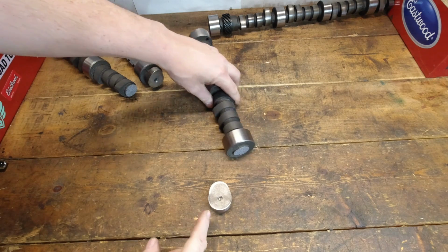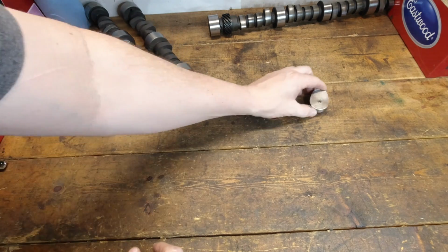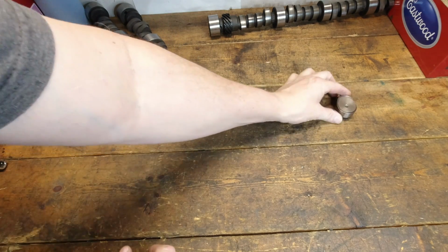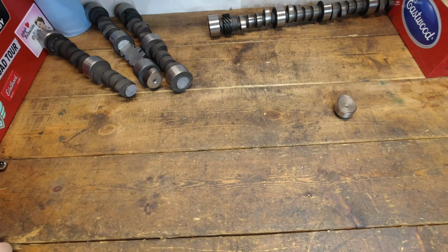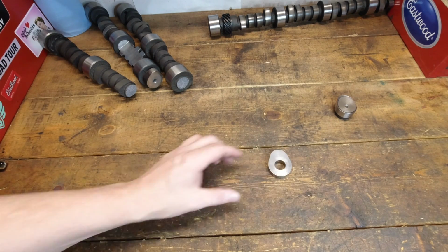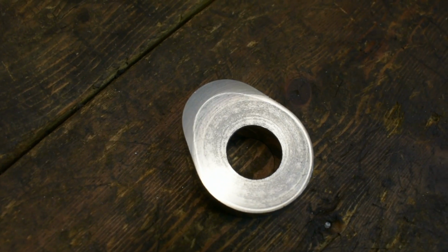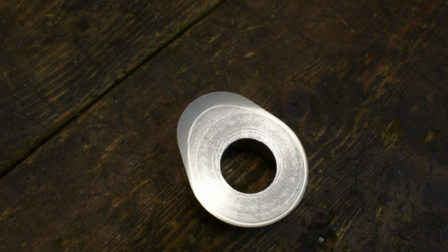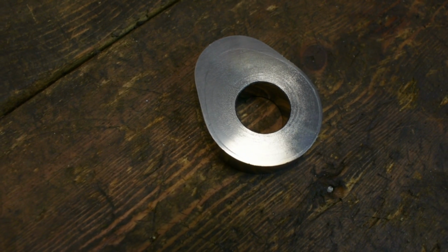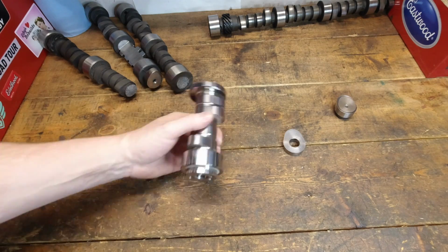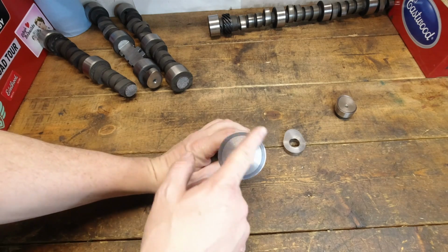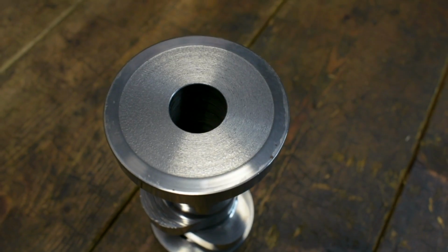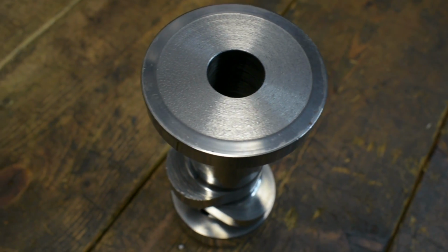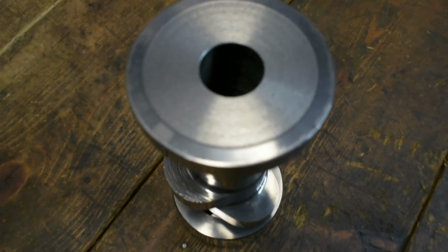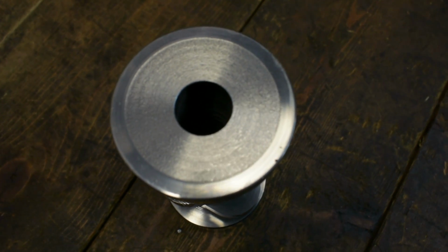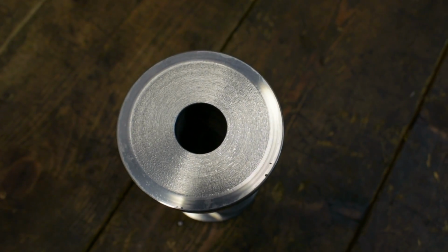And again, as we just saw in that example, they are a little bit different. The heat treating depth isn't near as aggressive as it is on a cast cam core, but it's fairly the same. If you look at this one here, that's just a cut of the lobe. You can tell again where the heat treating is on it. I'll get some close-ups of that because it's kind of hard to see it. This one's a nice one. It was just one that was cut down the journal, so you can see how deep the heat treating is on the journal, and everything in that softer, grayer, darker color is the softer part of the cam.